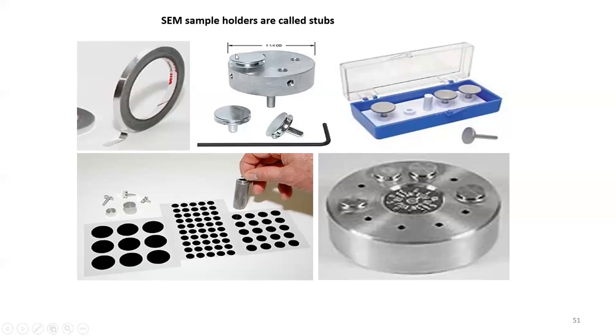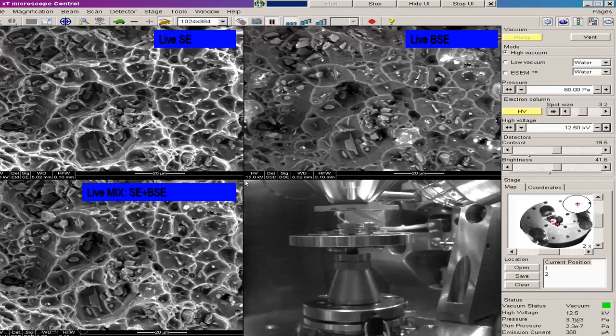And these are stubs on which the samples are kept. For SEM, you don't need very thin samples. You can place specimens the size of a brick even. That can go inside, depending on the size of the specimen chamber you use. These are the stubs on which you place your specimen, and these are conductive tabs. In the chamber, you have a CCD camera, and these are the detectors. This is a stage. You can place up to 7 samples on the stage here.